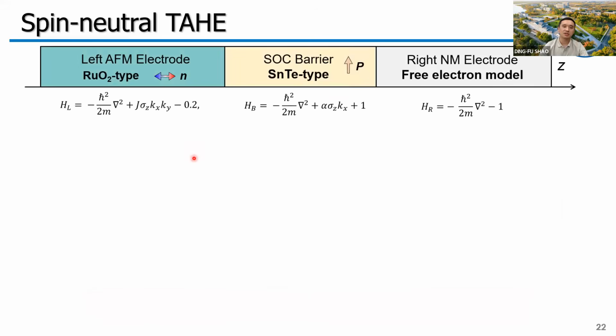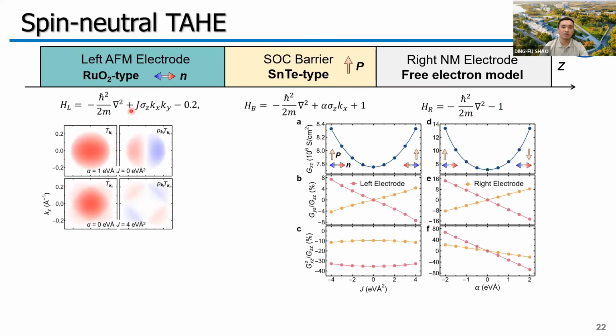In order to demonstrate this, we consider the tunnel junction where the components have these Hamiltonians. Here, J is a parameter to describe the spin splitting in the band structure of the ruthenium oxide, and alpha is a parameter to describe the Rashba-type spin-orbit coupling in the barrier. The right electrode has a free electron model. So we find if J is 0, which means no magnetism, or alpha is 0, which means no spin-orbit coupling, the transmission patterns are highly symmetric, leading to a 0 tunneling anomalous Hall effect.